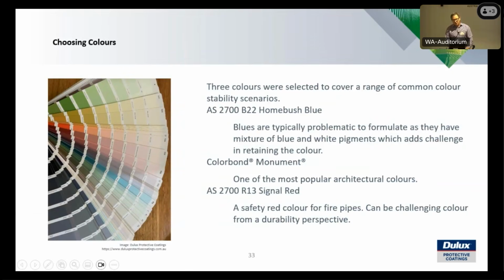And obviously, every colour will perform differently. You probably notice that when you paint around your house, inside and outside, or if you're like me, you look at paint systems wherever you go, and you look at faded systems and corrosion and that type of thing. But the three colours we chose for the testing were quite common colours, as well as quite bold colours where there's a lot of pigment used, to get a real clarity of test and an even test spread on different types of colour pigments. So Australian Standard 2700 B22 Homebush Blue, Colorbond Monument, which we may all have around our homes a little bit, and Australian Standard 2700 R13 Signal Red, which is used for a lot of identification, marking, safety, and in industry as well.